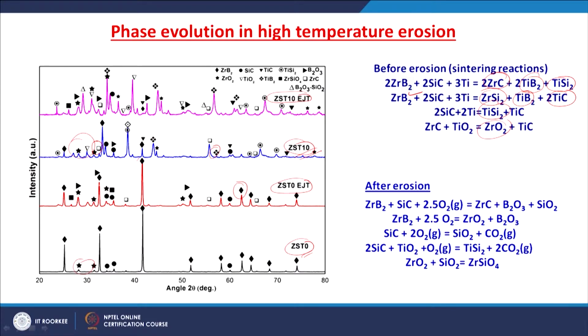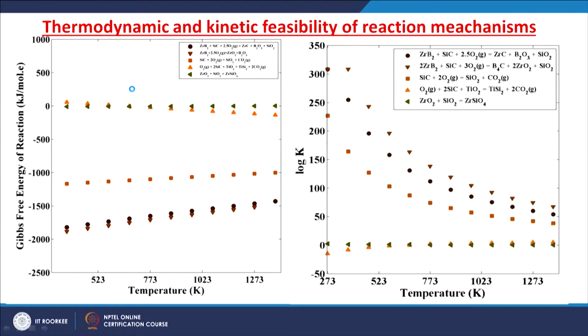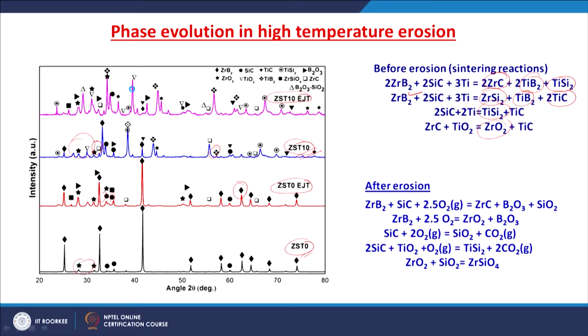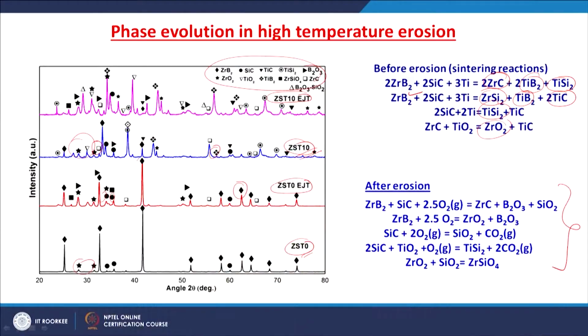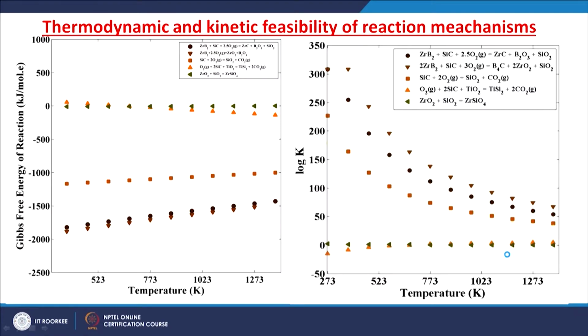Zirconium diboride, silicon carbide, and along with this we also have zirconium carbide, boron oxide, silicon oxide, and then titanium silicide or zirconium silicate. So, there are certain new phases formed because of the high temperature erosion. Let us understand such phase analysis by considering the thermodynamics and the kinetics. After sintering the erosion was done, and these are the probable reactions, because we are seeing all these reaction products. So, let us understand the feasibility of such reaction mechanisms by thermodynamics or kinetics.